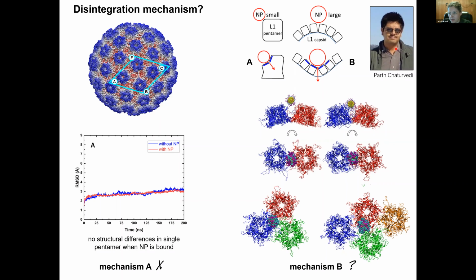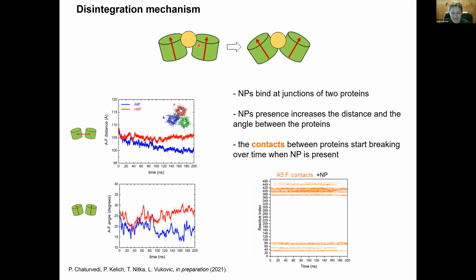The student in my group, Parth, who just defended his PhD, examined this mechanism B, and we looked at different segments of viral proteins, 2, 3, and 4 protein segments, and we exposed these segments to nanoparticles and then checked what happens over time. Is the nanoparticle presence going to lead to disassembly of these capsid segments? And that's what we observed, in fact, in simulations. Here is a very simple summary of what happened. When you have these viral proteins, first of all, we observed that the nanoparticle binds at the junctions of 2 proteins.